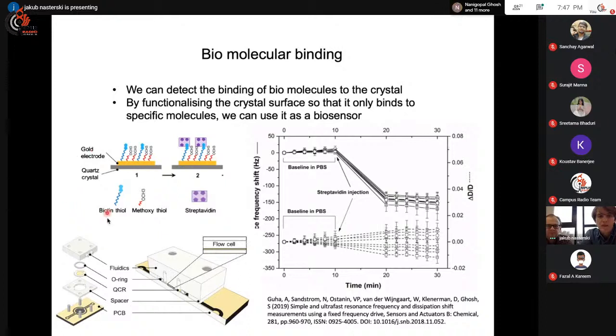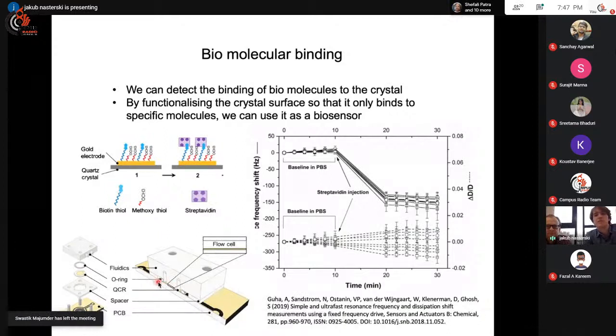We then construct a little microfluidic setup so that we flow liquid over the quartz crystal, which is functionalized with whatever it needs to be. And as we flow the sample, we monitor what happens to the frequency parameters. So here, as you see, this is the baseline. This is actually from one of the papers that our group has published. This is the baseline, and as we flow streptavidin, we see the frequency shift going down. So the mass binds, the resonance frequency decreases. This is the curve of dissipation, but it's not so important for this application.